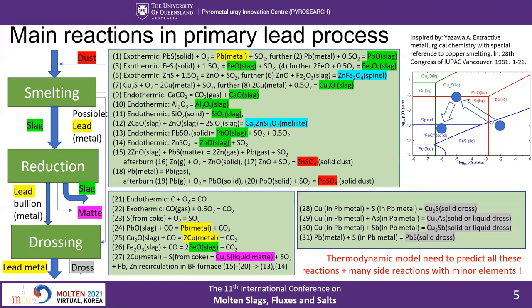The lead bullion produced at the reduction stage typically contains significant amounts of copper, sulfur, arsenic, antimony, and tin. In future, even more of these impurities are expected, particularly copper. A good thing about lead is its very low melting temperature. At low temperature, the solubility of these impurities decreases to low levels. Much of the copper can be precipitated out in the form of sulfide or arsenide, separating in liquid or solid form depending on temperature. Liquid sulfide is usually referred to as matte. A mixture of solid sulfides and arsenides is usually called dross. For certain compositions, copper-antimony and copper-tin compounds may also form, but their solubility is higher.